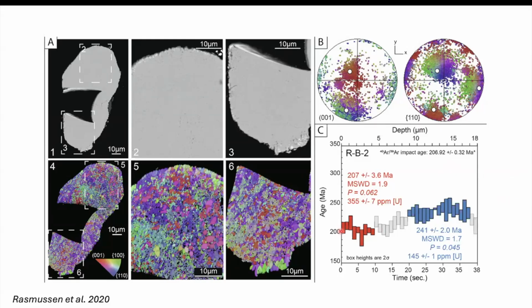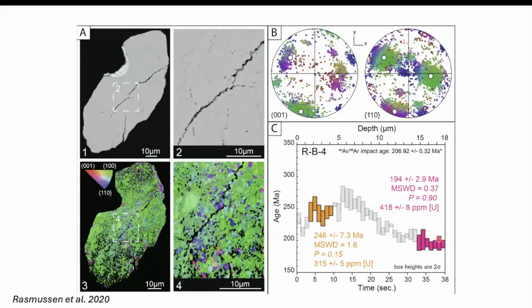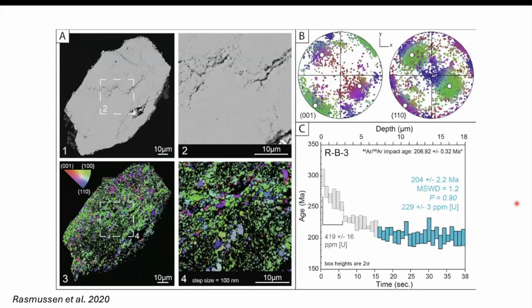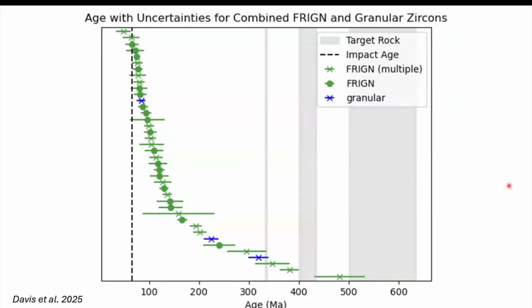And she found that if you do depth profiling of systematically oriented granular zircon, the age kind of changes throughout, and you can get multiple plateaus, some with an age that overlaps the impact age and some not. So sometimes you get really different ages. Sometimes you get really good ones. And then going back to what Jen Davis showed in her dissertation, you have some that give you the impact age, some granular zircons that give you target age, and some stuff in between.